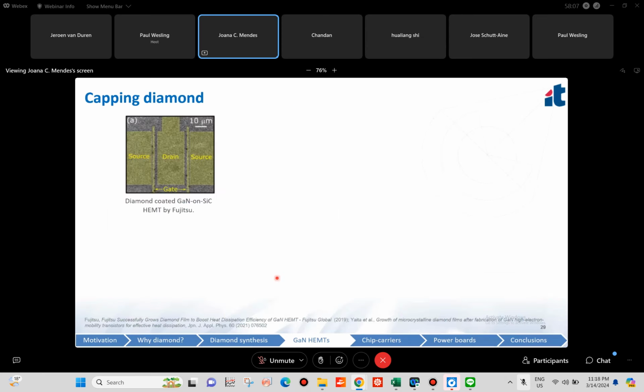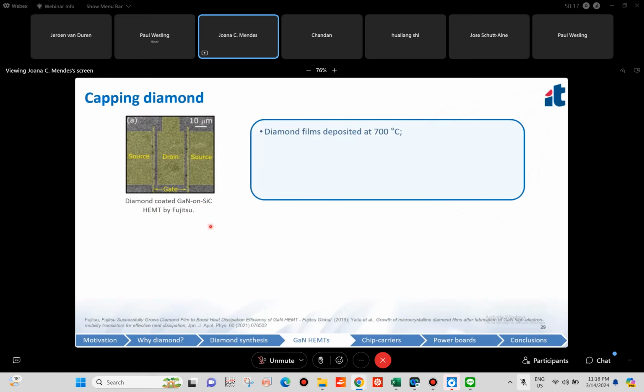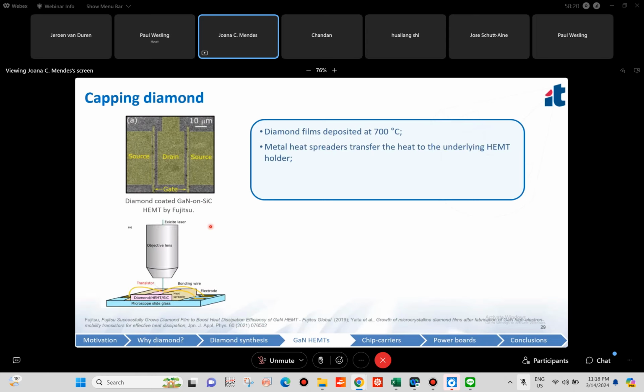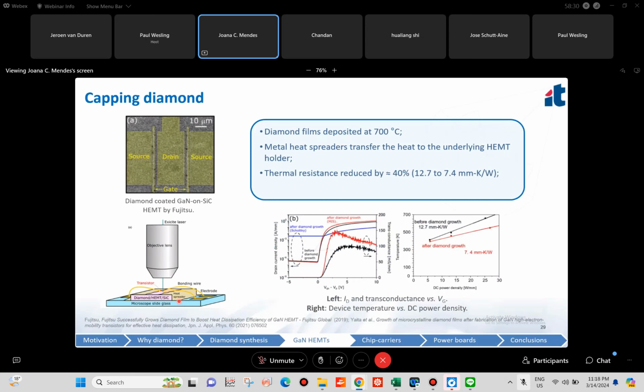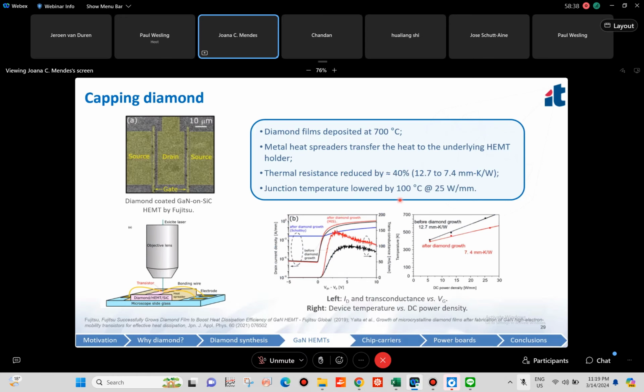And to start with the capping diamond, you see here the photo of a GaN on silicon carbide HEMT, coated with diamond by Fujitsu. They deposited diamond films at 700 degrees C, and they used heat spreaders to transfer the heat from the top of the device where it is generated all the way down to the underlying HEMT holder. And thereby they reduce the thermal resistance of the GaN HEMT by 40%. And they also lower the junction temperature by 100 degrees at 25 watt per millimeter power.